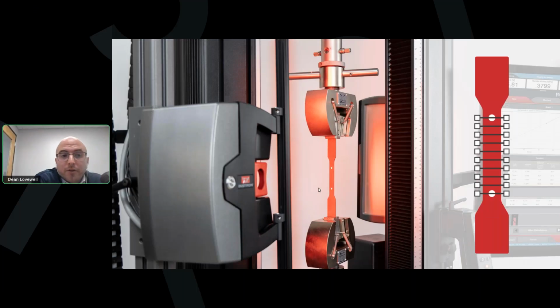And then with the AVE3 technology, which again, it's an optional feature to add on to the AVE3, this technology uses markless edge detection to track the width strain across all 32 gauge widths along the gauge length. So this provides the highest resolution width strain, ensuring that wherever strain occurs, it'll be captured and averaged into the result, giving the most repeatable R value determination possible. And by using markless edge detection, there's no need to apply any transverse markers or flags.